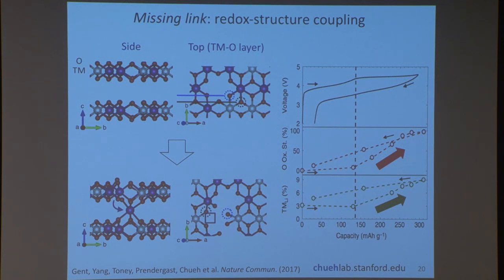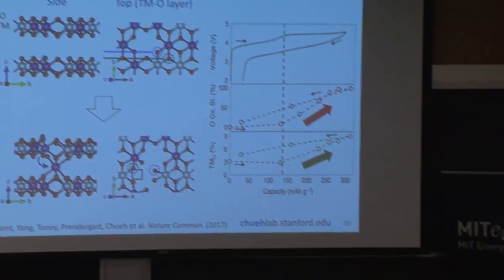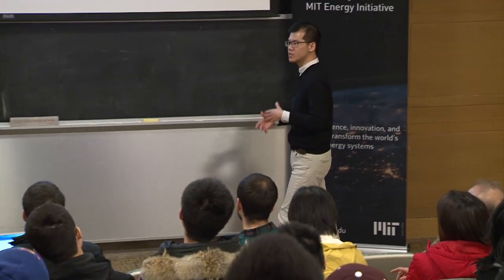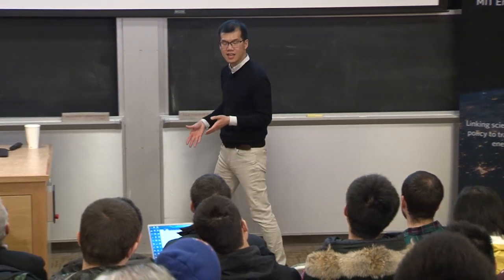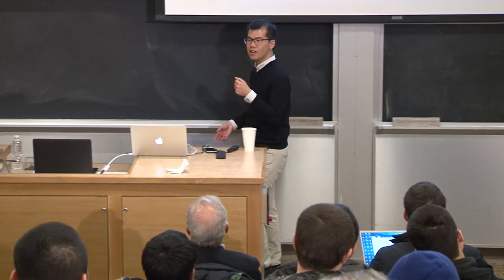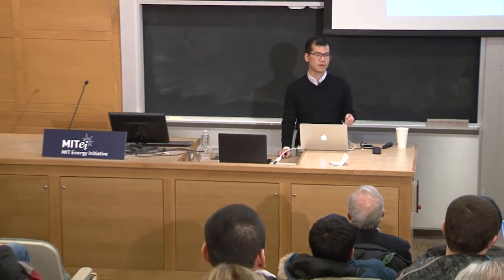This is important because if you can't oxidize oxygen, all you get is about 150 milliampere-hours per gram in this material, which is nothing to write home about. But it's this extra 150 you're getting that's amazing, and that comes from the simultaneous occurrence of oxygen getting oxidized, but also the transition metal moving, because if it doesn't move, then this will likely just come off as oxygen and you can't cycle it back because you permanently lost the oxygen. So it's really the simultaneous occurrence and the stabilization by forming the cation vacancy, which is really quite interesting as a beneficial defect in this material.